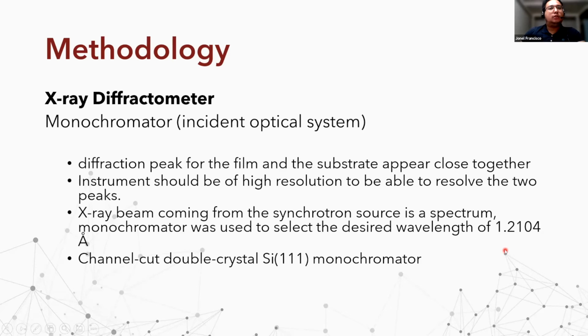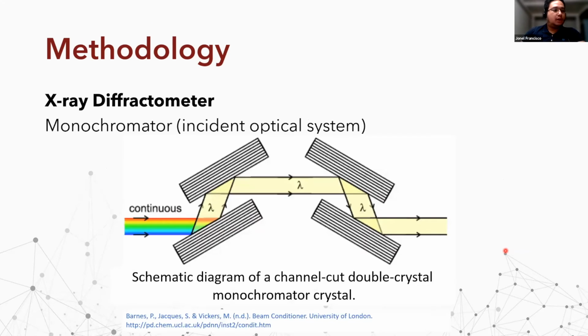In this study, a channel cut double crystal silicon 111 monochromator was employed to obtain a narrow beam of incident X-ray. This is the schematic diagram for our monochromator. We know that the X-ray beam is a continuous spectrum which contains a range of wavelengths that could interfere with the measurement. After passing through this monochromating crystal, the exiting beam is highly parallel and monochromatic. To explain why it is called a channel cut double crystal, this setup is contained in a single crystal, with another reflection made by the second crystal. That's why it is a double crystal monochromator system.